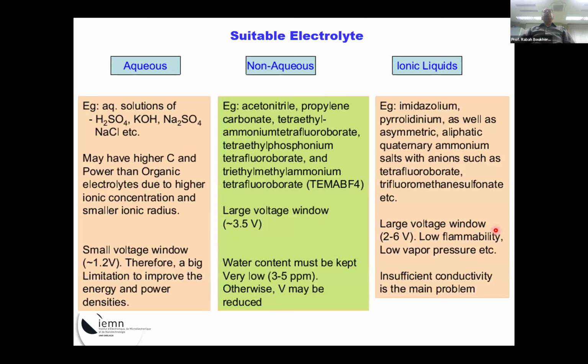So what you can do, you can move to non-aqueous, and essentially acetonitrile, propylene carbonate here. You can see so many of them. So you have a large voltage window, which is about 3.5 volts, but there is always a problem, because most of these solvents can easily capture water, so then you will be running the same problem if you have a mix of water and your organic solvent. So you have continuously to work under controlled conditions in a way you don't have any water traces in your organic solvent.